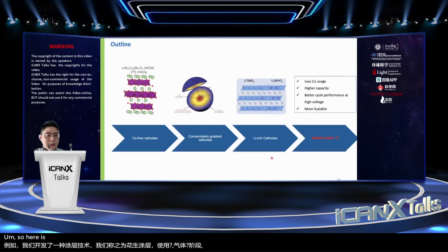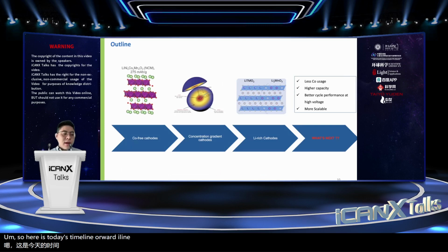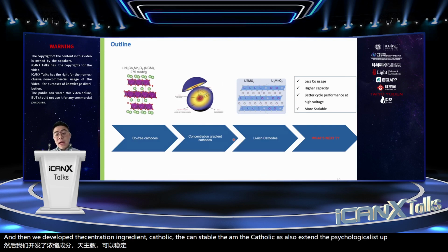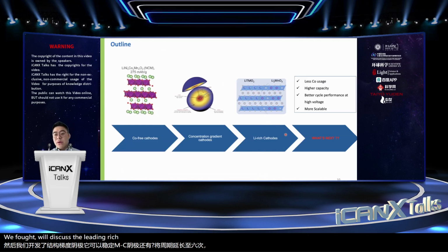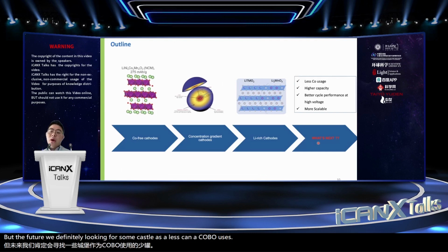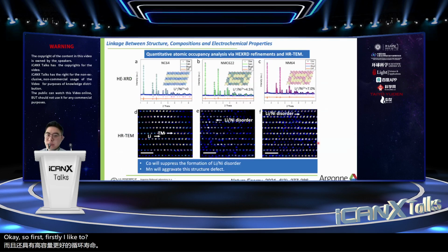So here is today's outline. First I will discuss the cobalt-free cathode materials. By removing cobalt from the cathode, we can decrease the battery cost by about 25%. And then we developed the concentration gradient cathode that can stabilize the NMC cathode and also extend the cycle life up to 6 times. We will further discuss the lithium-rich cathode for lower cost and higher energy density. For the future, we're definitely looking for some cathodes that have less cobalt usage and also have high capacity and better cycle life. Okay, so firstly, I'd like to discuss the cobalt-free cathode.